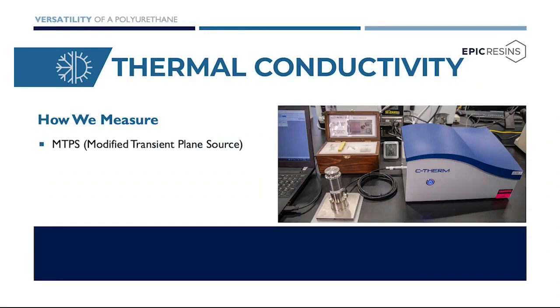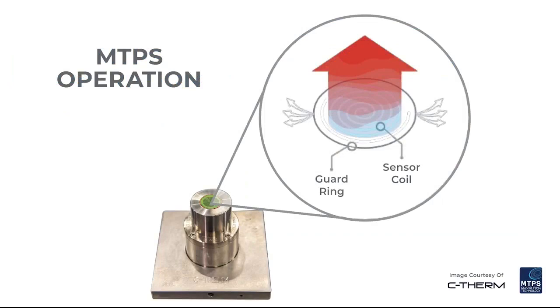Heat transfer and thermal conductivity are measured using a modified transient plane source method. This is a diagram of how the method works. A known current is applied to the sensor's spiral heating element, providing a small amount of heat. A guard ring surrounds the sensor coil to support a one-dimensional heat transfer into the sample. The applied current results in a rise in temperature at the interface between the sensor and the sample. The rate of increase in the sensor voltage is used to determine the thermal properties of the sample. The voltage is factory calibrated to temperature.